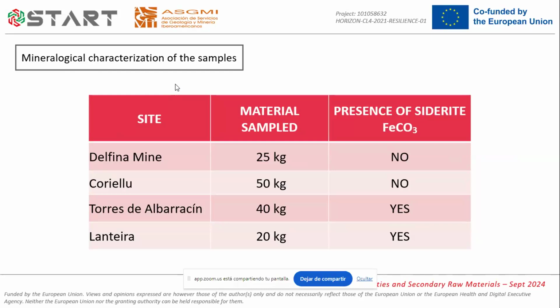Another important parameter that has to be taken into account is the content or not of siderite. It is important because, as I will explain later, the presence of this mineral will decide the type of process to be followed in the laboratory. So we have the Delfina mine, where we took, as Concha has said, 25 kilograms, and Coriellu mine, where we took 50 kilograms, and none of them had siderite in the paragenesis. And on the other hand, we have Torres de Albarracín with 40 kilograms sampled, and Lanteira with 20 kilograms. Both of them having siderite that will be treated as a gangue.